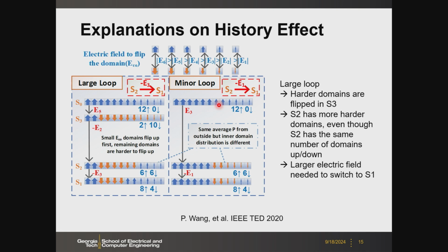In the smaller loop, the minor loop, we directly flip those 6 easier domains. So here we also have 6 up and 6 down. You see that internally, the distribution is different. In the next pulse, we flip 2 more up, but for the larger loop we flip those 2, which are harder, than here where we flip those 2. That's why we need to apply a larger voltage in this case. Even though we're doing the same transition from S2 to S1, and the amount of polarization switching is the same, the switching voltage is different.